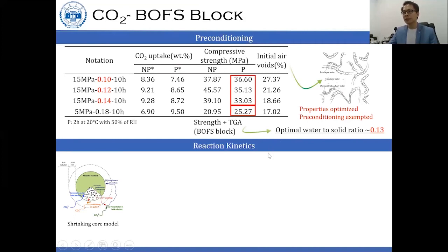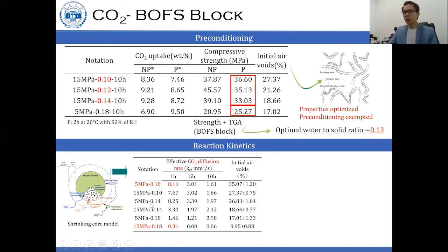So we also did some reaction kinetics through the shrinking core model. And we have calculated the effective CO2 diffusion rate. For the lowest molding pressure and the lowest water to solid ratio, we found that the diffusion rate is 8.16. If you compare to the high molding pressure and high water to solid ratio, it is almost 30 times lower than this sample.